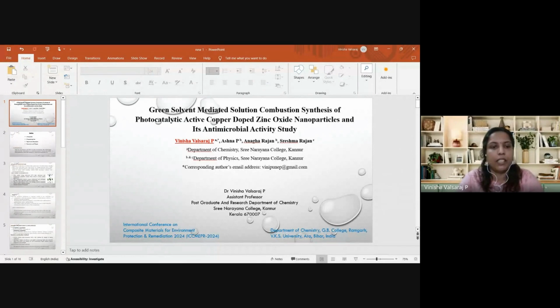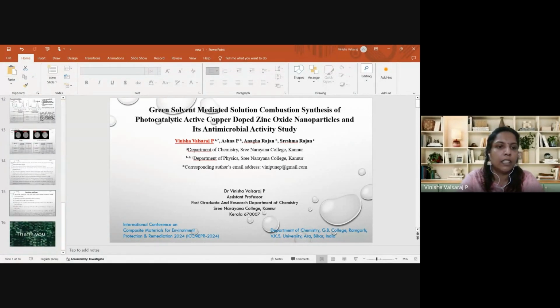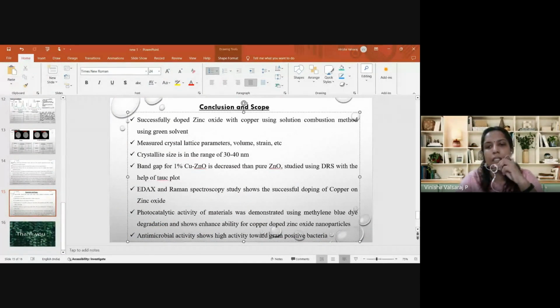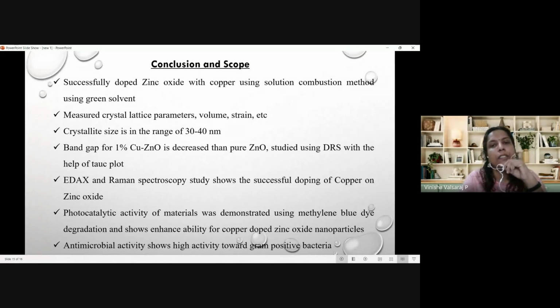So, coming to the conclusion, we successfully doped zinc oxide with copper using the solution combustion method with a green solvent. Using XRD, we measured the crystalline parameters, and it confirmed the wurtzite structure of zinc oxide and copper-doped zinc oxide. The crystallite size is around 30 to 40 nanometers, and the band gap is decreased in the case of copper doping, as studied using DRS and the Tauc plot. EDAX and Raman spectroscopy show the successful doping of copper on zinc oxide.